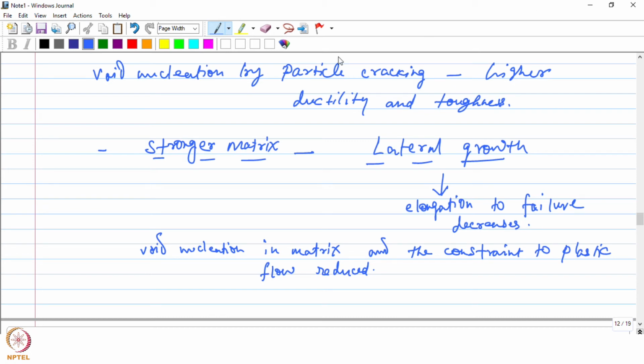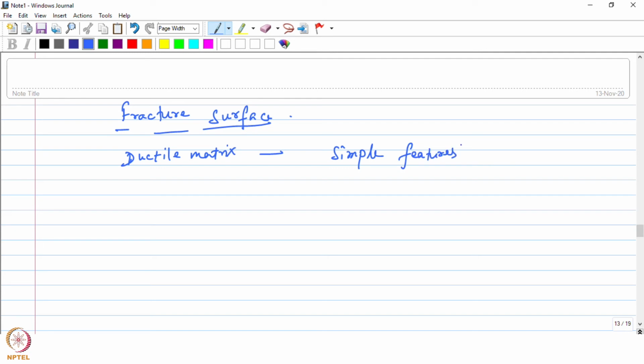And this difference between the nucleation modes can also be identified by looking at the fracture surface, which can be observed in a scanning electron microscope, which shows the topography, and it can show the differences that you have on a particular surface. Okay, so for the ductile matrix, if you look at the fracture surface, you will have simple features like those voids or dimples, because it has occurred through a void nucleation and growth kind of mechanism.